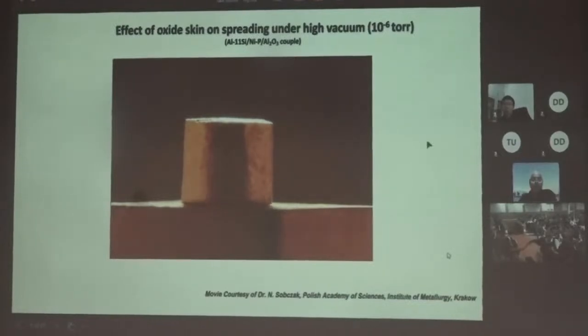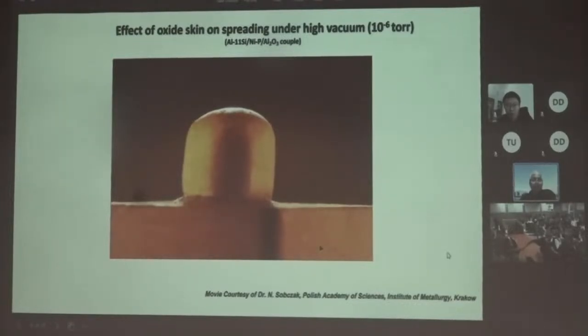We know that little droplets have oxide skin. So here, looking at aluminum silicon on an alumina substrate with nickel phosphorus coating, look at what happens to the oxide layer here. You will see that the oxide is really tenacious and the liquid is actually beginning to seep under it. So essentially the oxide forms a cap and liquid begins to spread underneath. And this is just a very small droplet, 2 or 3 millimeters in size, under really high vacuum at high temperatures. So these are the kind of issues that complicate measurements of wettability in many systems. So how do you actually examine these things?